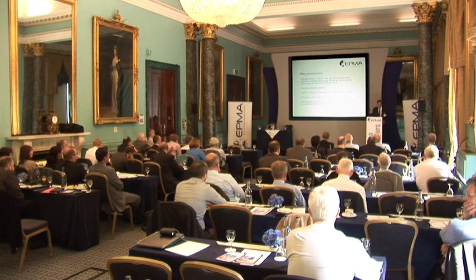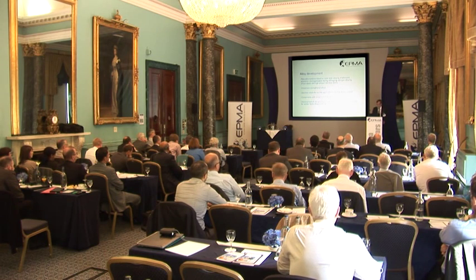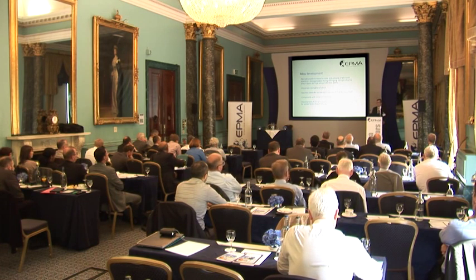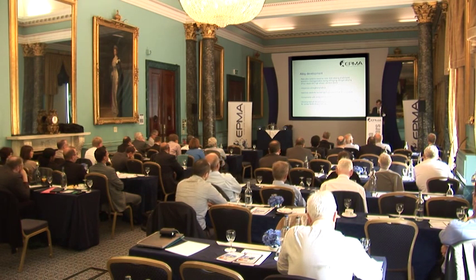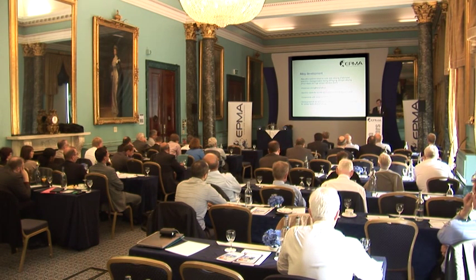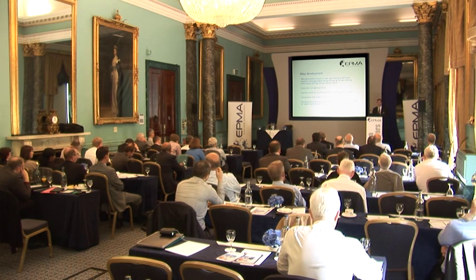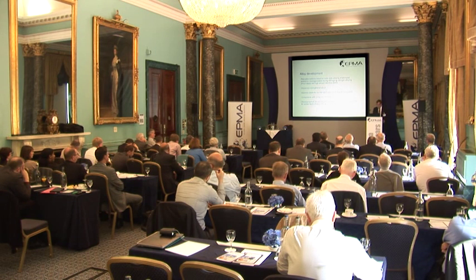You have dispersion strengthened alloys. I mentioned stainless steel applications with high boron content. We have a tremendous lot of nuclear waste to take care of. Components with compound structure. And also, as I mentioned in some examples, the potential to develop new alloy systems with functional properties oriented for certain fields of application. With present process metallurgy, you are limited by, for example, hot workability and cold formability. You can virtually avoid that by the PM route.